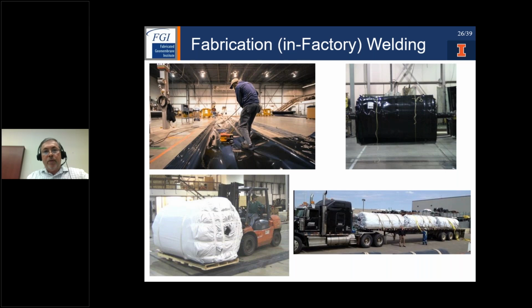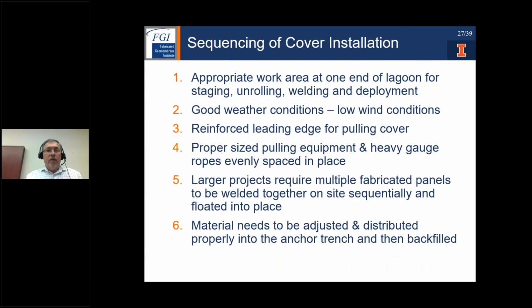The in-plant fabrication, as you can see, again, just a couple pictures of some of our plants, but the picture on the top left, we're welding in ideal conditions, so room temperature, clean floors, tensiometers, inline testing with the fabrication. And then these are wound up onto larger panels. We can typically, for these digesters, make panels, depending on the material, weight and thickness, anywhere between 20 and 30,000 square feet. And then these large panels, as you can see on the bottom pictures, are then put on trucks and transported to site.